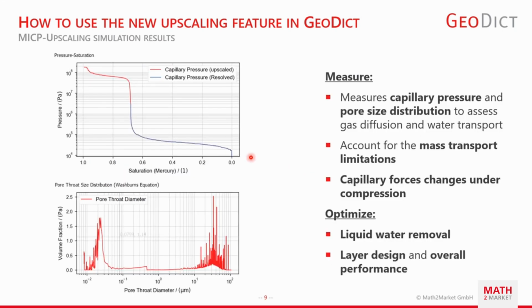The results would look like this. So you would obtain a capillary pressure curve that consists of a resolved part and an unresolved, or so-called upscaled, part. So in principle, the blue part of the structure consists of the GDL that gets saturated, while the red part consists of the MPL that gets saturated once the pressure reaches a certain level. Based on that, you can, of course, also derive the pore throat diameters of the structure, where you would then have the pore size distribution for the GDL resolved and, for the unresolved part, also the pore throat diameters.